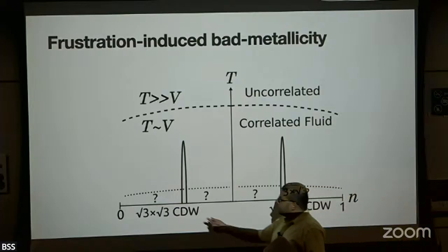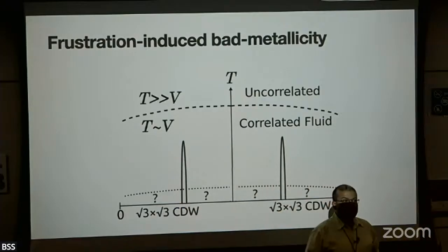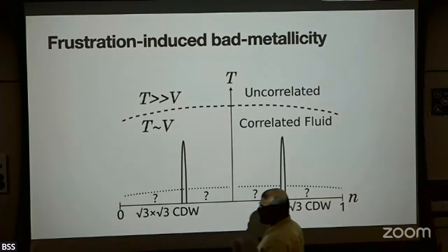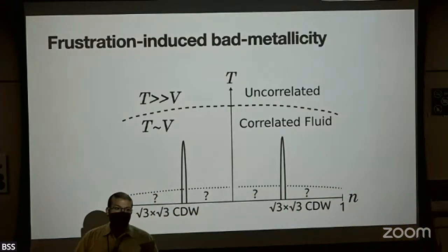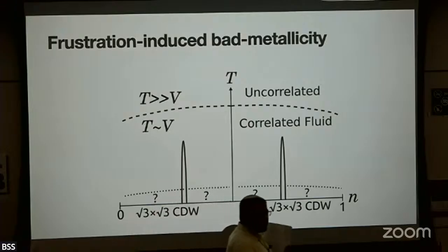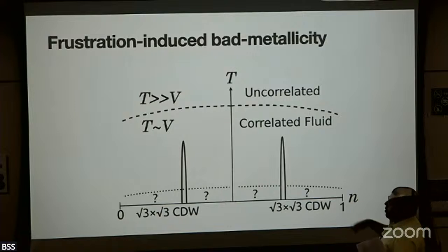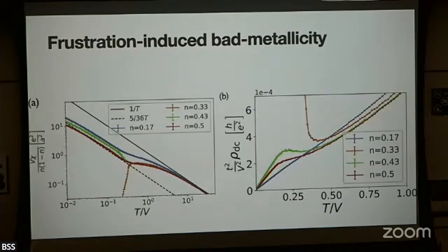Now, as I will show you, there's a very strong tendency at a filling of 1/3 and 2/3 for the system to develop charge density-like correlations, again, because when the nearest neighbor repulsion is strong, you want to avoid each other, and that leads to all kinds of crystalline order, okay? And so, of course, in this setup, when you're doing perturbation theory in little t, everything that I say will only be limited by temperatures of the order of t. I can't go below an energy scale of the order of t. Okay, so this is what the result looks like.